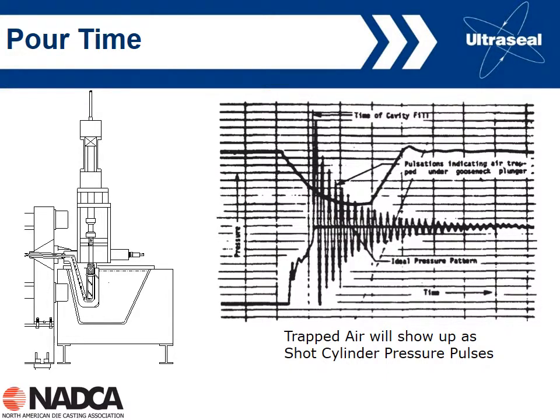If we do have this problem, if we do entrap air here at the tip, we get this characteristic up and down in the pressure in the shot cylinder. So we need to watch out for this. If we see this kind of characteristic behavior, it is very characteristic of entrapping air down here at the tip during fill-in of the gooseneck.